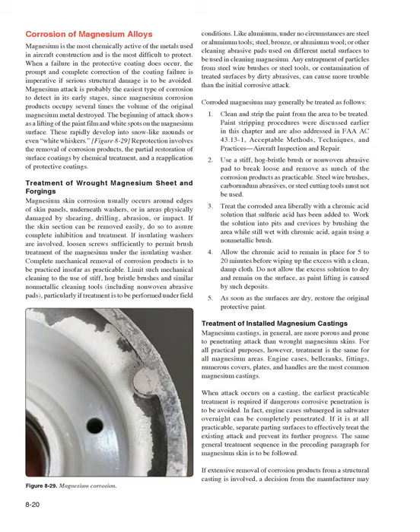3. Treat the corroded area liberally with a chromic acid solution that sulfuric acid has been added to. Work the solution into pits and crevices by brushing the area while still wet with chromic acid, again using a non-metallic brush. 4. Allow the chromic acid to remain in place for 5 to 20 minutes before wiping up the excess with a clean, damp cloth. Do not allow the excess solution to dry and remain on the surface, as paint lifting is caused by such deposits. 5. As soon as the surfaces are dry, restore the original protective paint.